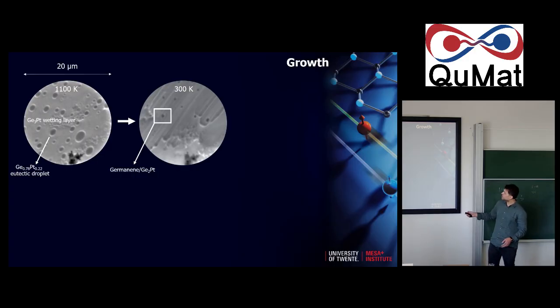And we can make them very big right now because the trick is to make these droplets as big as you can. You can do that by staying at this high temperature for very, very long times, about a few hours, for example. Then the droplets coalesce, they get bigger, and when you do the decomposition, your 2D flake is also very big.